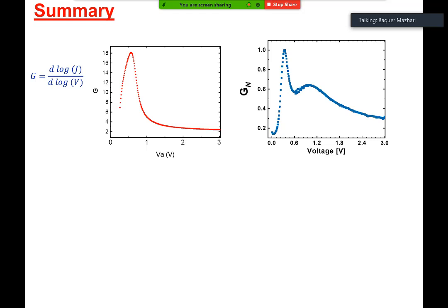So what we are suggesting is that from the IV characteristics that you measure, you can get some very interesting additional data if you simply look at the derivative of the log-log plot. And this is the signature of a healthy device with one single peak. You can calculate the built-in voltage. If you see additional peaks, a strong reason for that could be the presence of traps. And you could make several inferences regarding the traps, the nature of the traps, their location, and their concentration through this analysis.